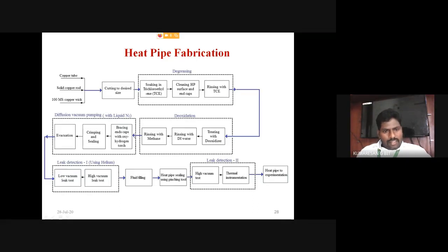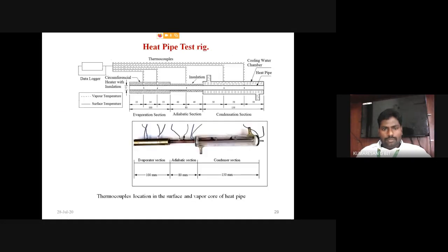Okay, then these ends are sealed with the help of the brazing process. Then crimping and sealing take place. Then with the help of the diffusion vacuum pumping devices, the evacuation of the tube is done. Okay, then this completed end-sealed tube is taken for the leak detection process. Here there are two leak detection tests. First, the leak detection takes place under a low vacuum pressure. Then it is taken at high vacuum pressure. Then finally, the fluid is filled inside the heat pipe. Then the end of the heat pipe is sealed using the pinching tool.